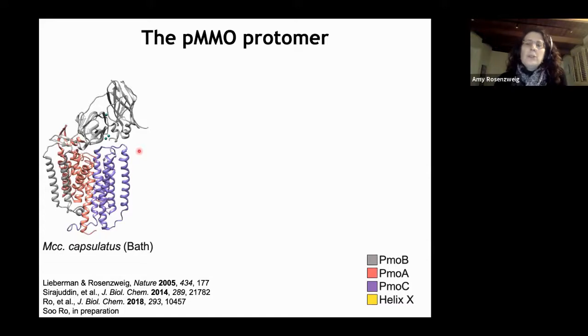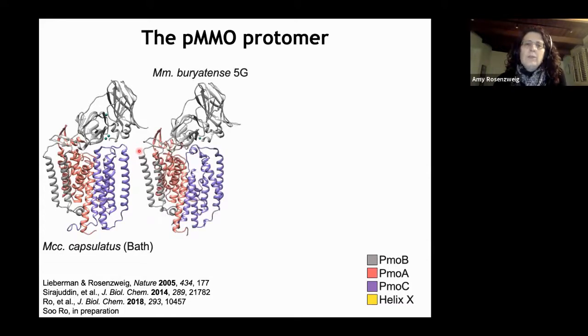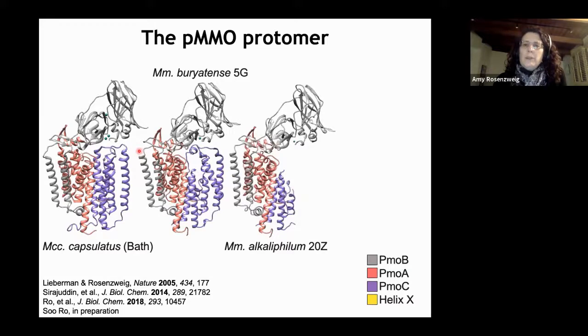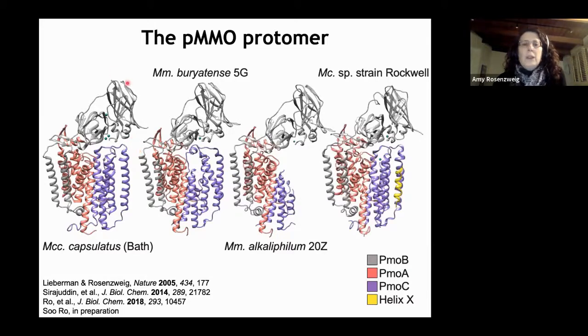And we've determined the crystal structures of PMMOs from a range of different methanotrophs. So here are some of the other structures that we've obtained. I'll point out that this PmoC subunit, shown here in purple, seems to be the most flexible. So its conformation changes a bit in the different structures. And in the case of this structure here, it's actually primarily disordered. We can't even see it in the electron density.